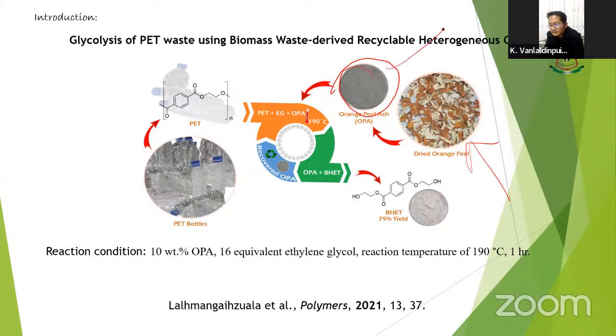for glycolysis of PET. The reaction was carried out at 190 degrees Celsius with 16 equivalent of ethylene glycol. And the reaction is completed in 30 minutes also, but the best result was obtained with 1 hour of reaction time. And one advantage of this catalyst is that it could be recycled and reused for up to 5 cycles.